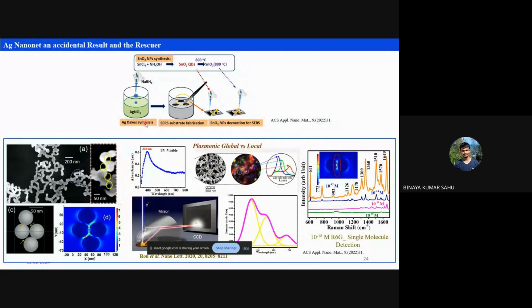This is a very accidental outcome, of course. What we were doing, we were adding silver nitrate and ammonium hydroxide. We added extra ammonium hydroxide to the silver nitrate. Then what could we see? Some kind of flake structure was floating over the solution. Out of curiosity, we collected that flake structure and saw it under the FESEM, and it was nothing but a beautiful silver net kind of structure.